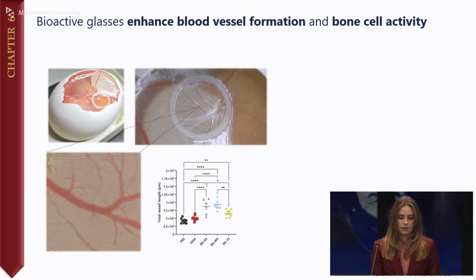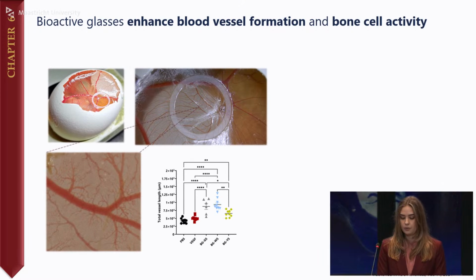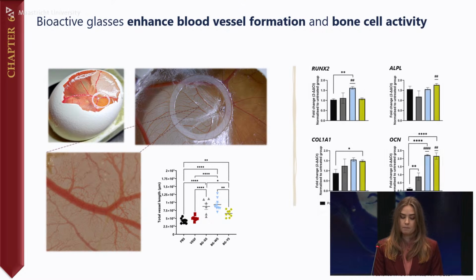We observed that all three bioactive glass formulations enhance blood vessel formation in the developing chicken embryo model. At the same time, we observed that these glasses stimulated bone-forming processes. They had a positive influence on expression of genes related to bone formation. However, these effects were not equal.